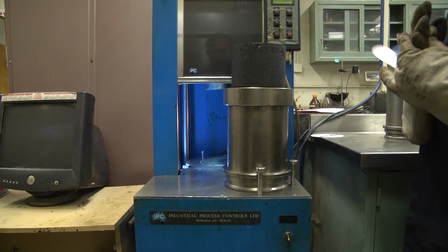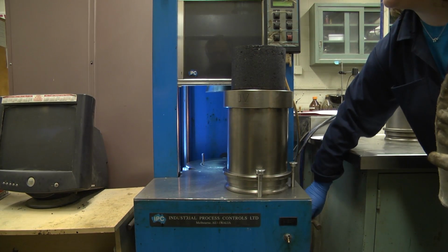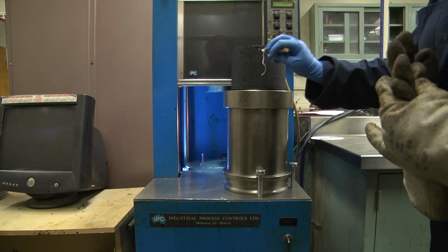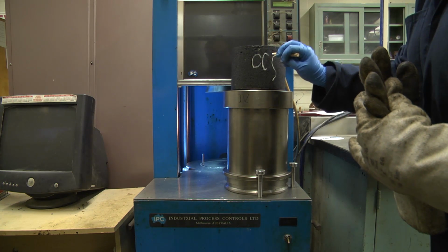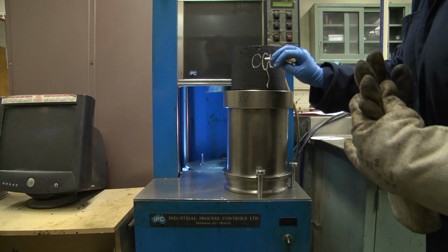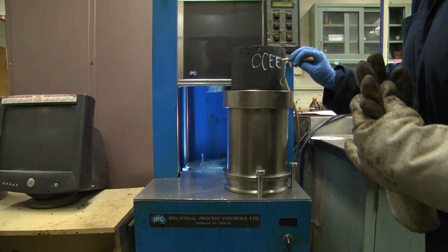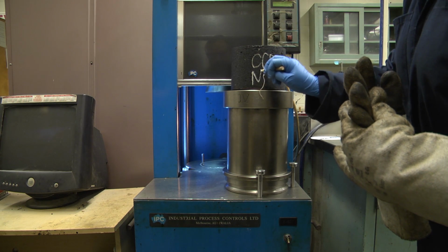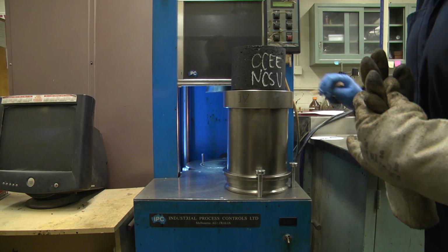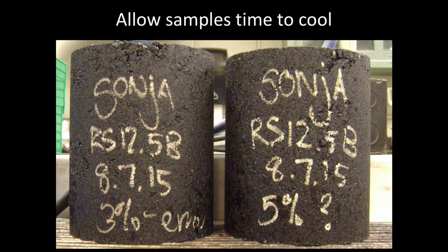Remove the paper disc from the top of the specimen. Label the sample to allow easy identification. For example, aggregate type, binder type, and binder content are commonly used to identify samples. Allow the sample to cool for 5 to 10 minutes and then move the sample to a level area for storage. Remove the bottom disc and allow the specimen to fully cool before subjecting it to volumetric or performance testing.